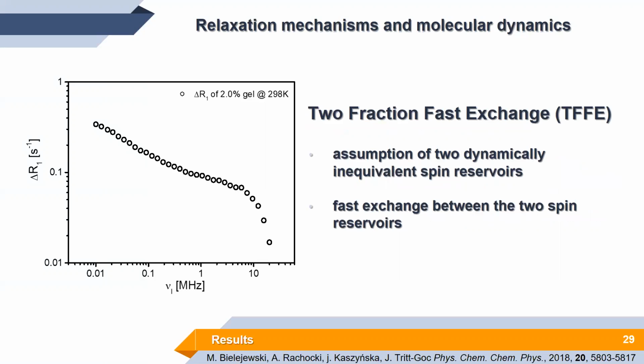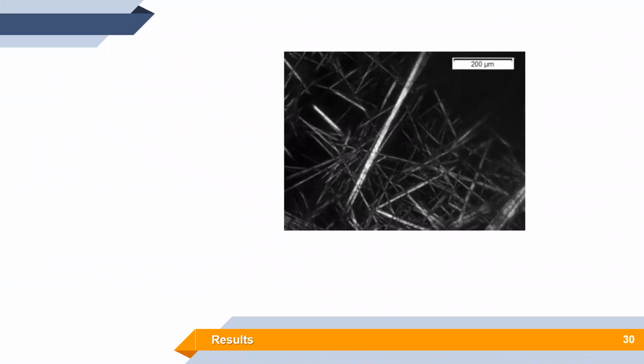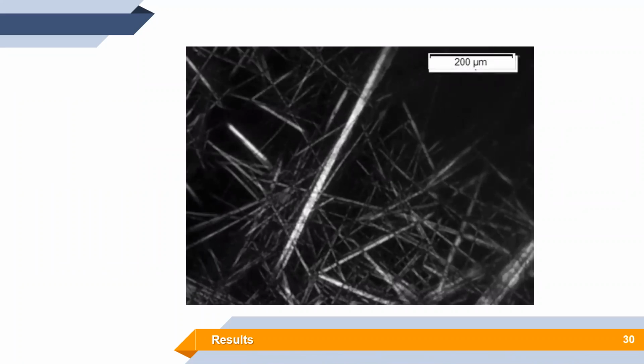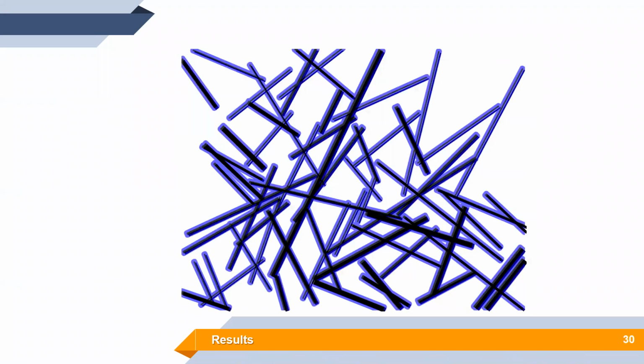The second one, the two-fraction fast exchange model, assumes the existence of at least two dynamically inequivalent spin reservoirs, which are interacting with each other. Moreover, they are in a fast exchange regime, fast in terms of the T1 relaxation time. And if we take a closer look at the internal structure of our ionogels, even if we restrict to hydrogels, then